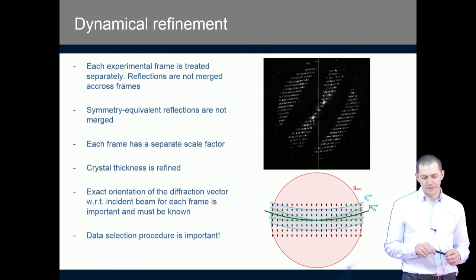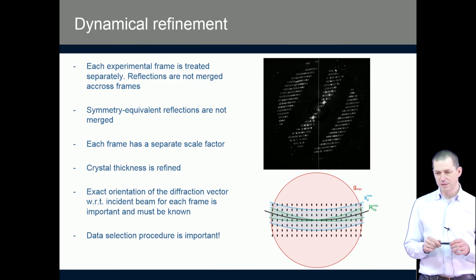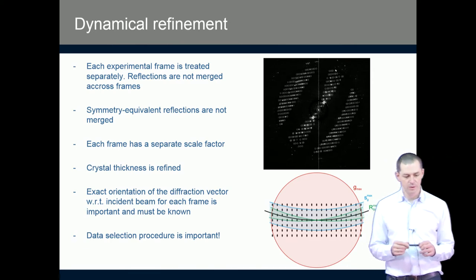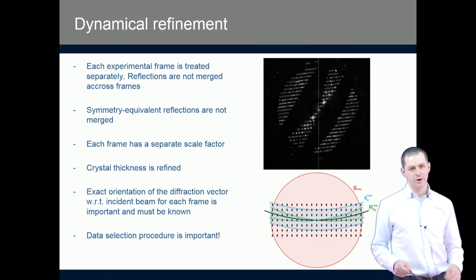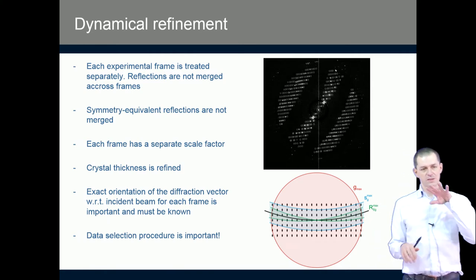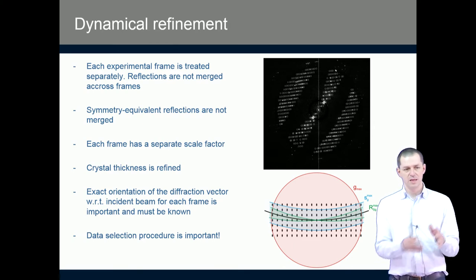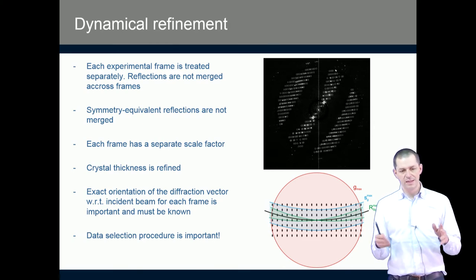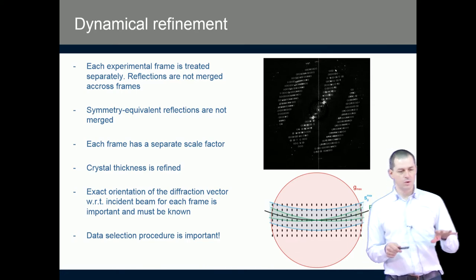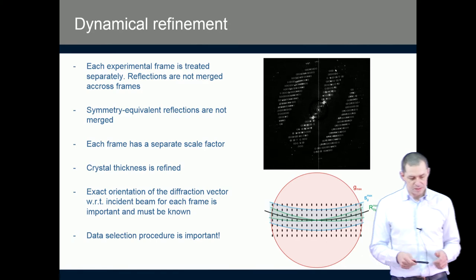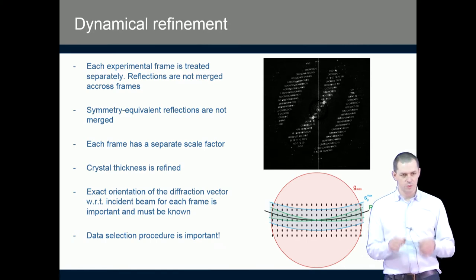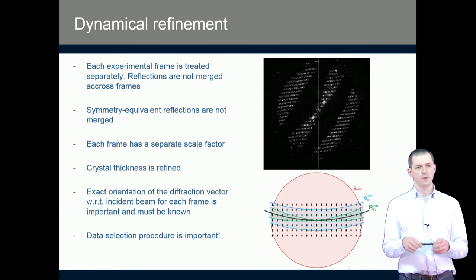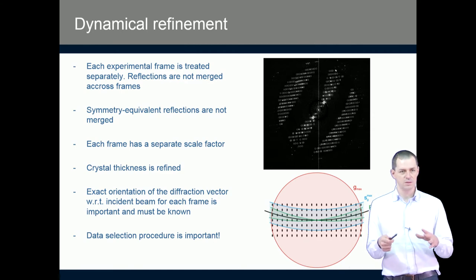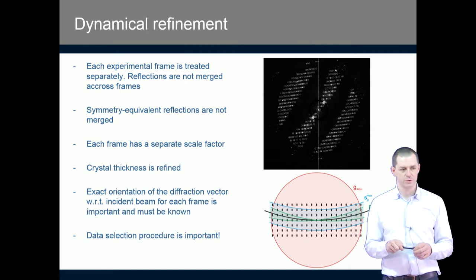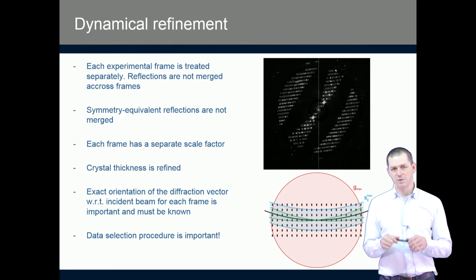There are a few more details that make the dynamical refinement different from the kinematical one. The first one is that each experimental frame is treated separately. So the intensities are extracted on a frame by frame basis, and the intensities are compared on each frame separately. Symmetry equivalent reflections are not merged, so there is no R-int in this case, because the dynamical effects do not follow the symmetry. They are dependent on the exact orientation of the crystal, so two symmetry equivalent reflections need not have the same intensity.